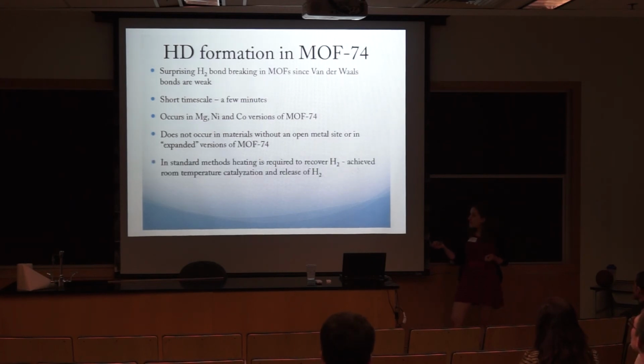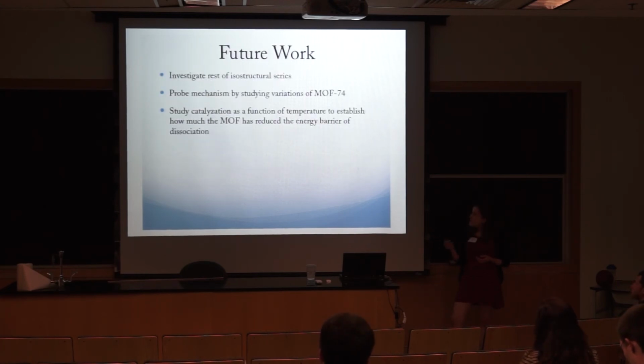In standard methods of catalyzing hydrogen on metal surfaces, you have to heat it up to get the atomic hydrogen to come off. In our method, it happens at room temperature, so you don't need to do anything. In the future, we'd like to investigate the rest of the isostructural series, so the rest of the metals. We want to probe the mechanism by studying different variations of MOF-74. We can build different versions. And we also want to study the catalyzation as a function of temperature to try to get to what temperature the dissociation is happening at.